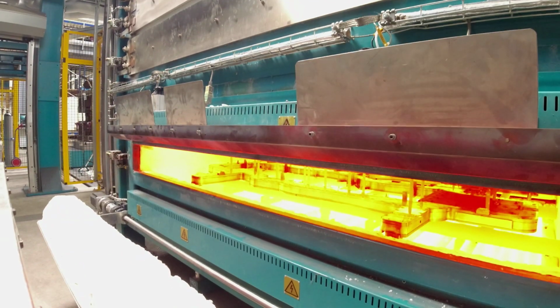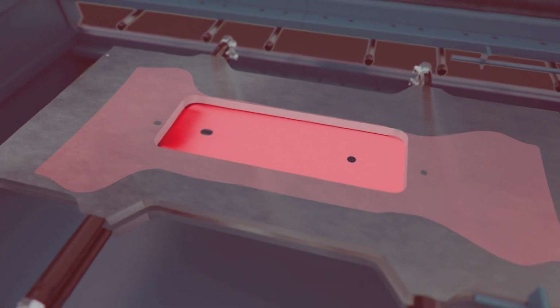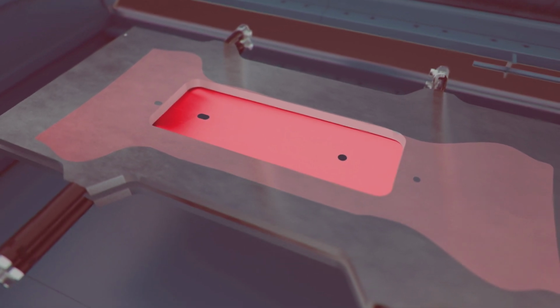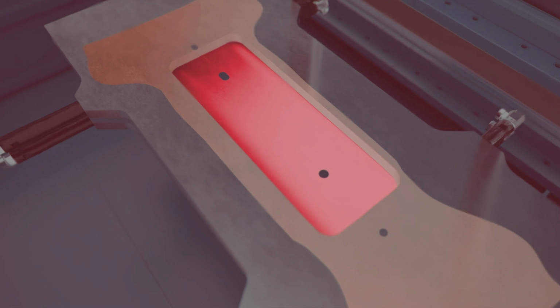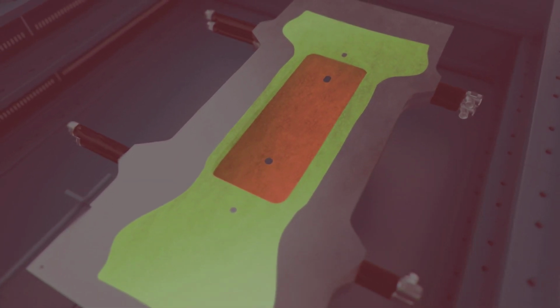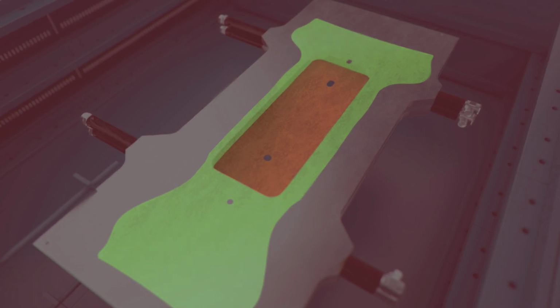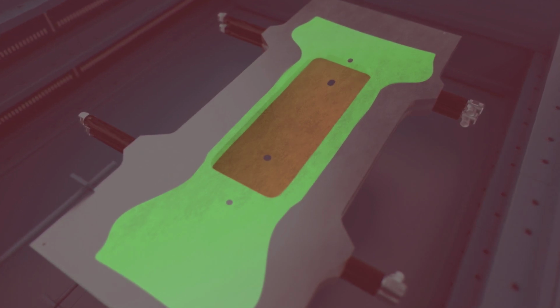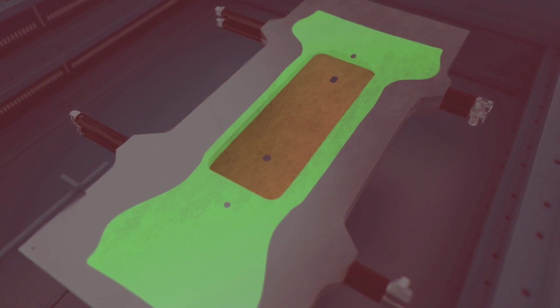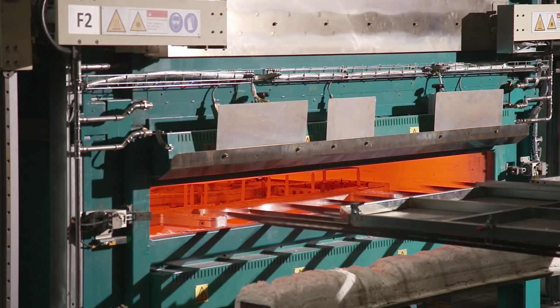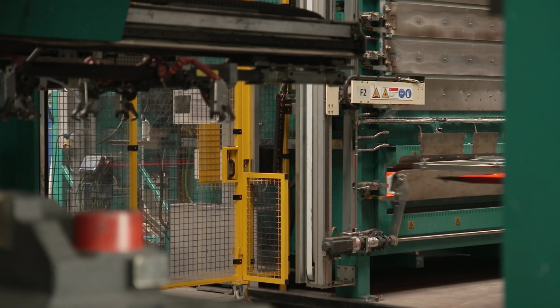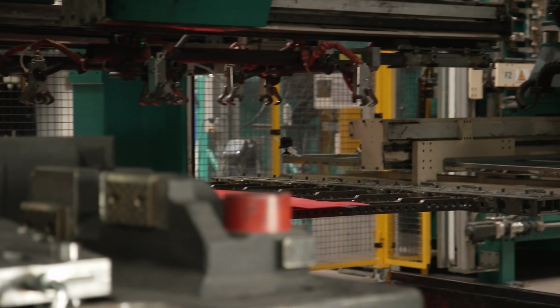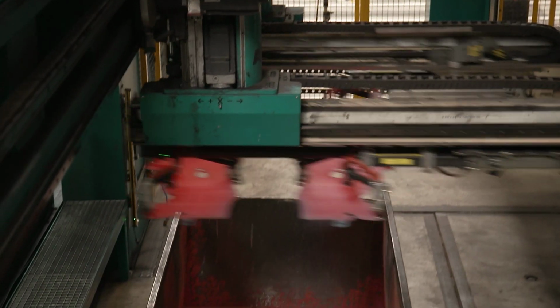The templates are in this lower box. The sheet metal is placed between the two templates. The templates are cooled down with 70 degrees Celsius water. In the area covered by the templates, the temperature of the sheet metal drops to around 450 degrees Celsius. As a result, the metal in this area adopts the softer ferrite structure. In the middle area, which is not cooled, the sheet continues to be heated at over 900 degrees Celsius and remains in the austenite structure. The robot takes the piece out of the temper box and carries it to the press. At this moment, it has two different temperature zones with two different metal structures.